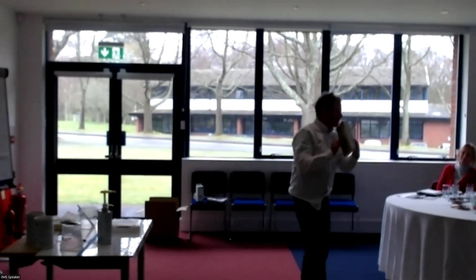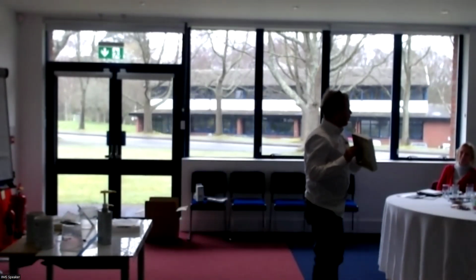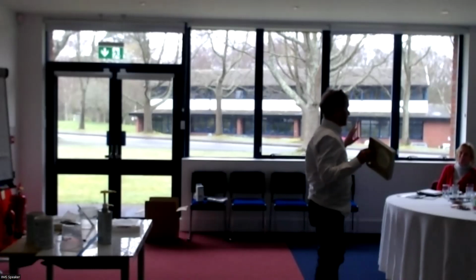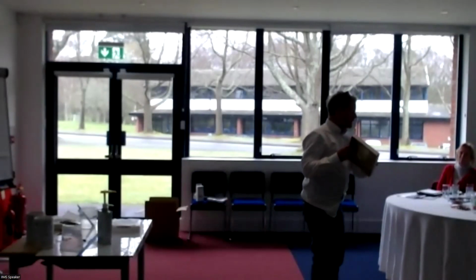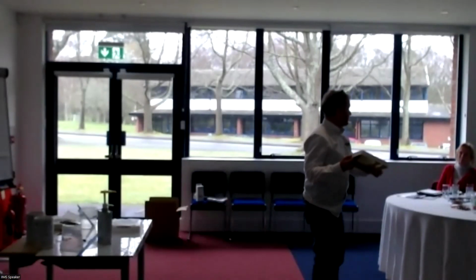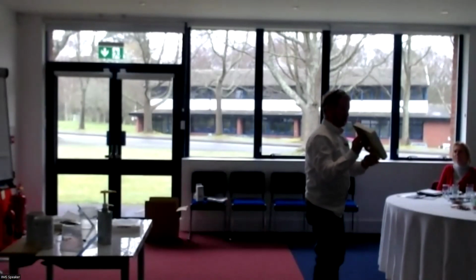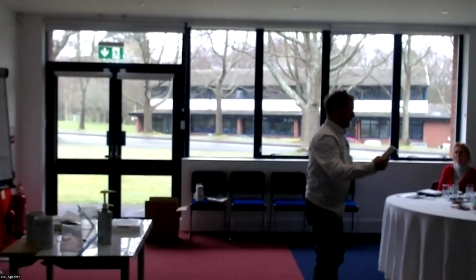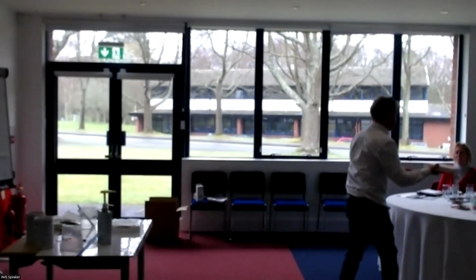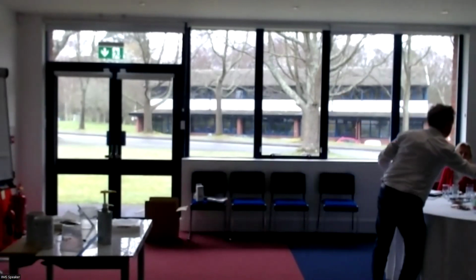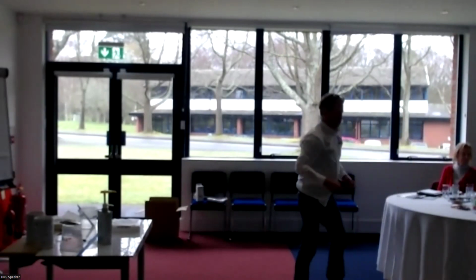So that's actually filled. We've got a filler that's pure white. It's glass bubble. And then sanded, it's the same density roughly as mahogany. And that's flattened off. The deck edge repair is made good. That needs a bit of fine filling, and this corner bit needs a bit of filler added to it. But pass that around if you want. There are some sharp edges on, so just be a little bit careful.